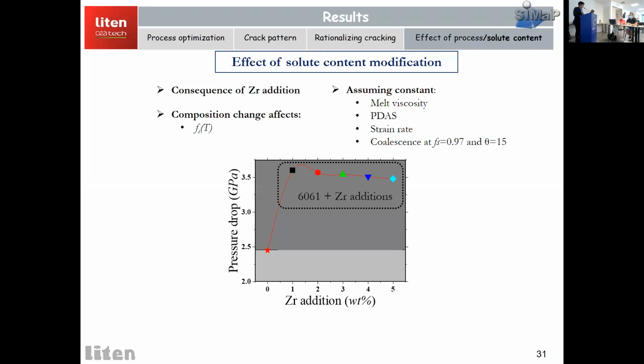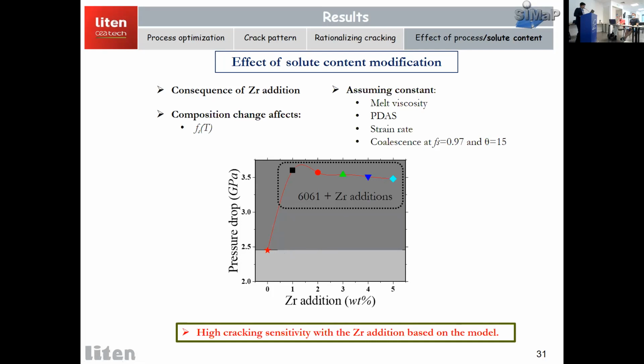So we end up getting a pressure drop as a function of different zirconium additions. For the standard 6061 aluminum alloy, we were at 2.5 gigapascals of pressure drop. And after we increase the zirconium additions, we clearly see that the pressure drop is increasing rapidly. We end up getting high crack sensitivity with zirconium addition. This is contrary to what is presented in the literature.